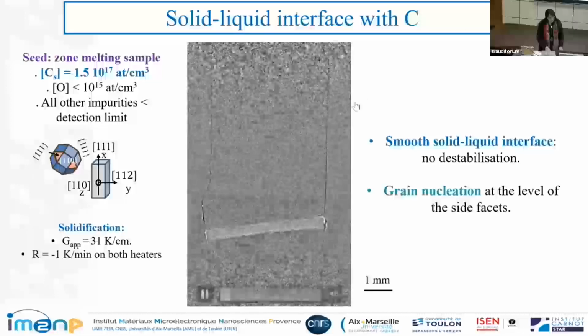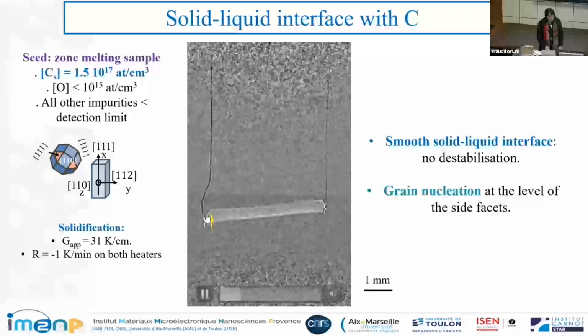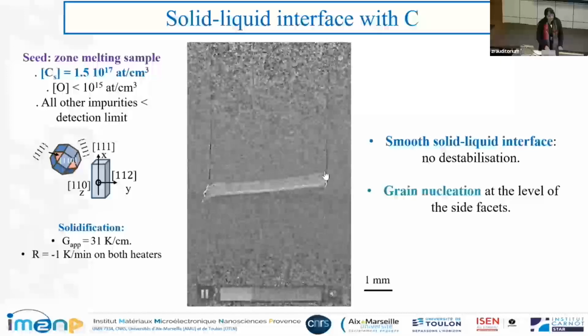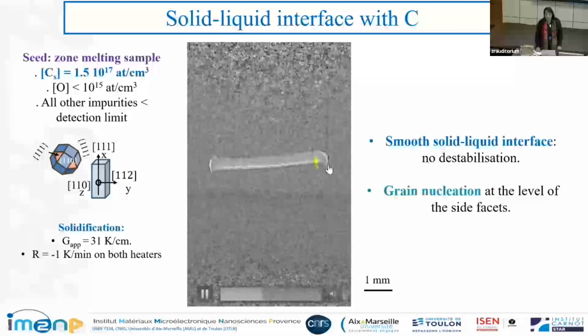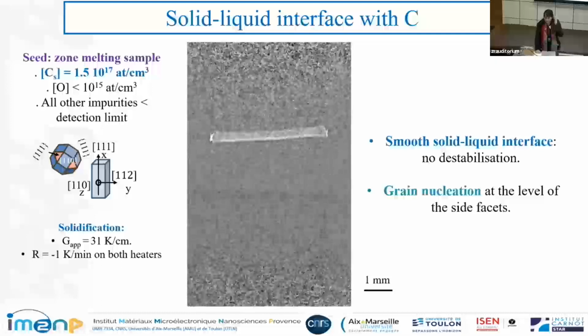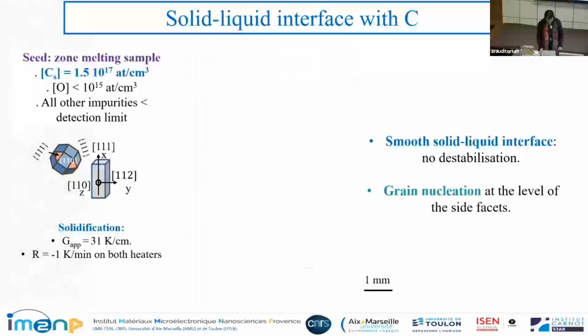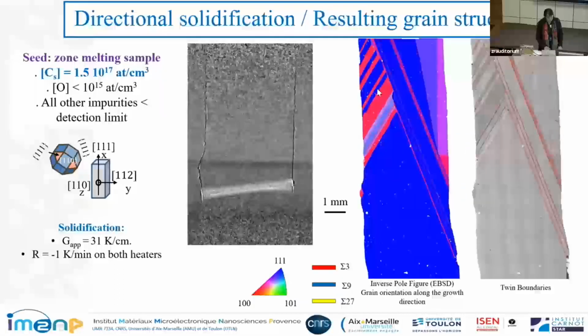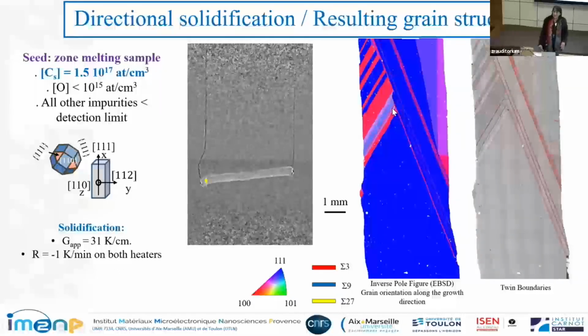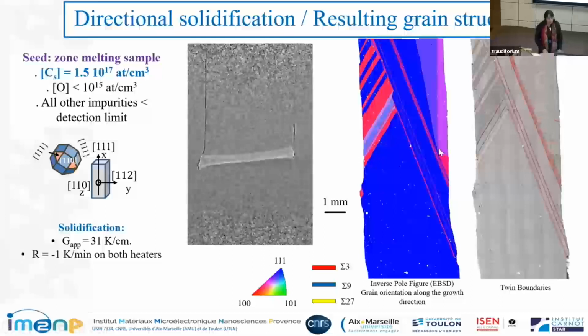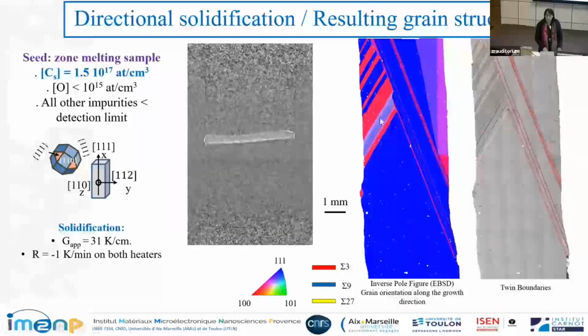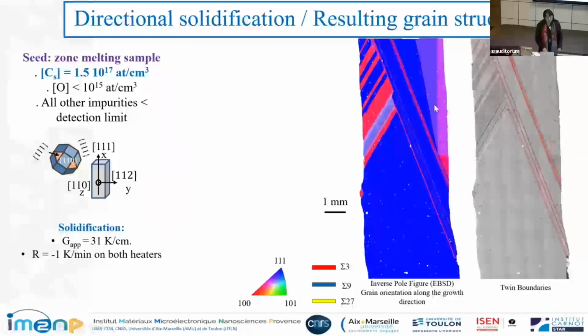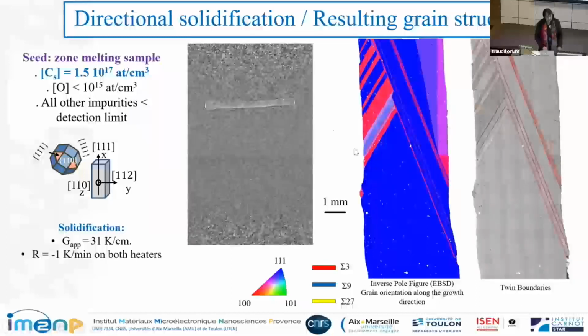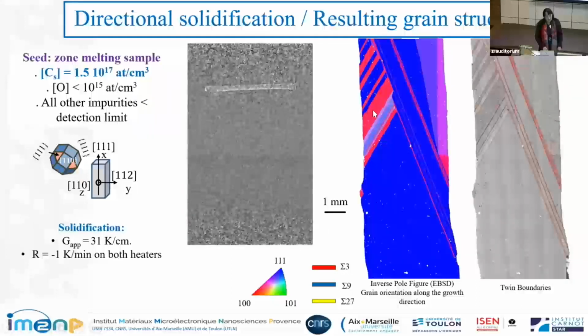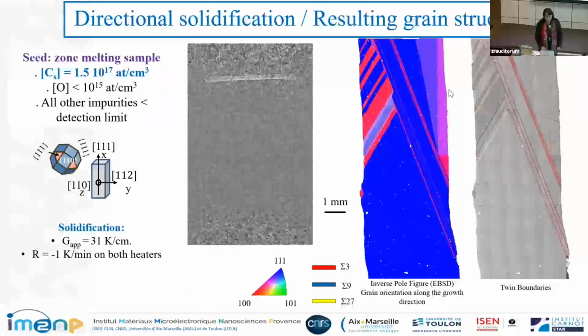But what you can see is that at the edges here, we have crystallographic facets and regular nucleation of grains at the level of these crystallographic facets. In fact, the grain structure at the end of solidification looks like this, where you have indeed the formation of grains on both edges at the level of the facets, which are here regularly during solidification.